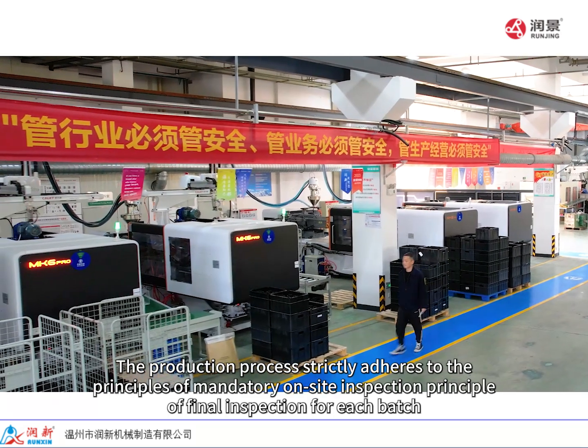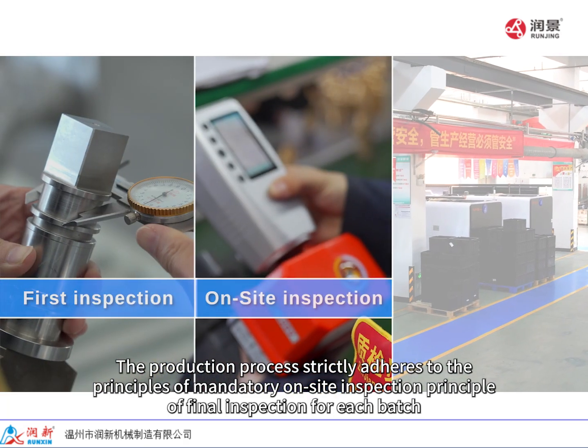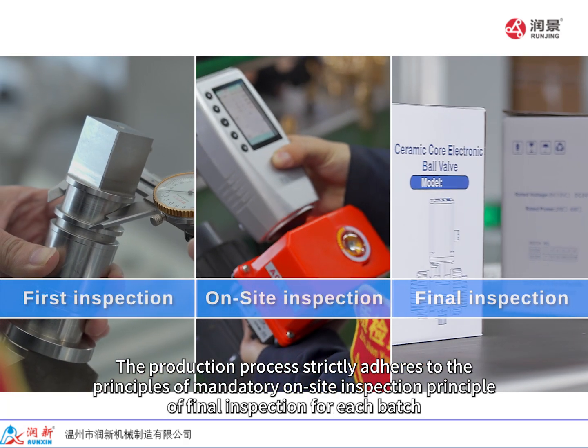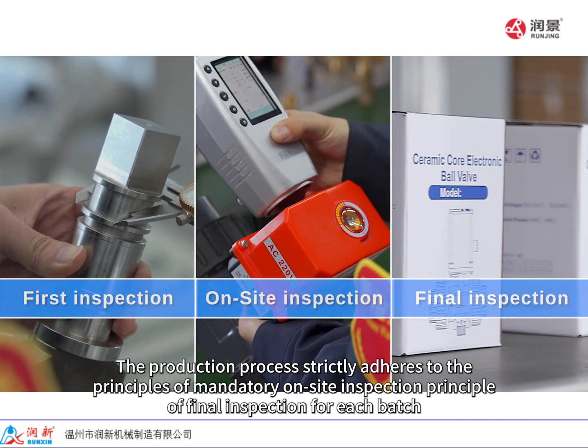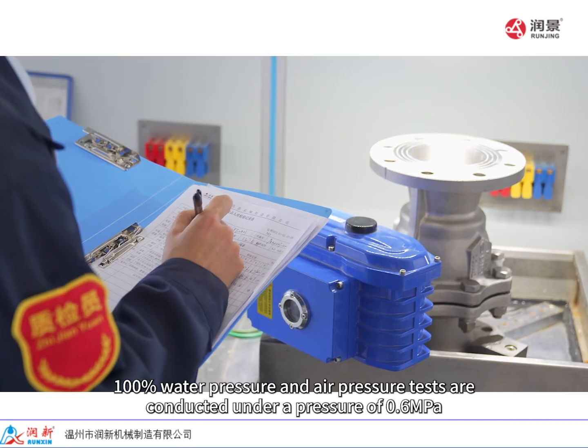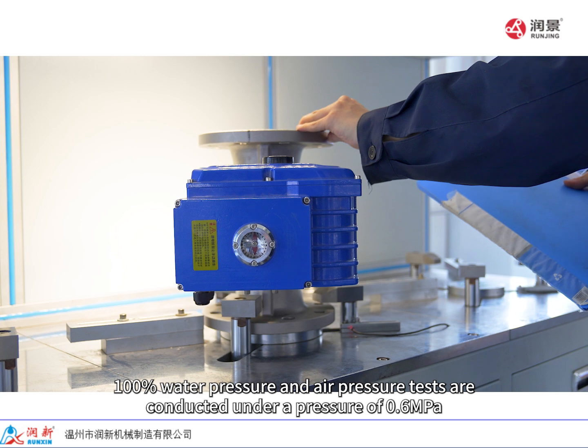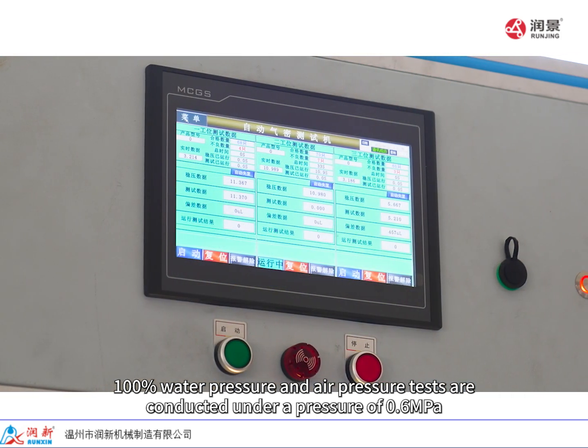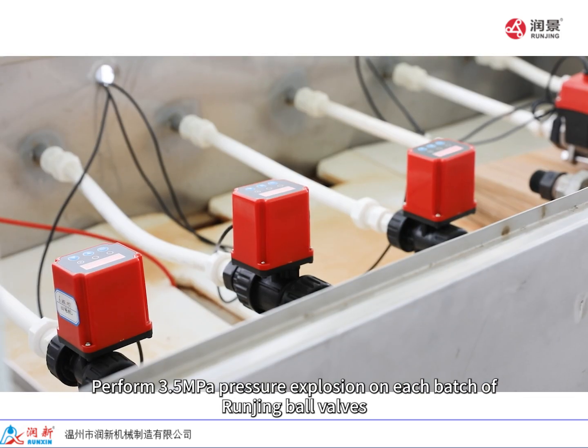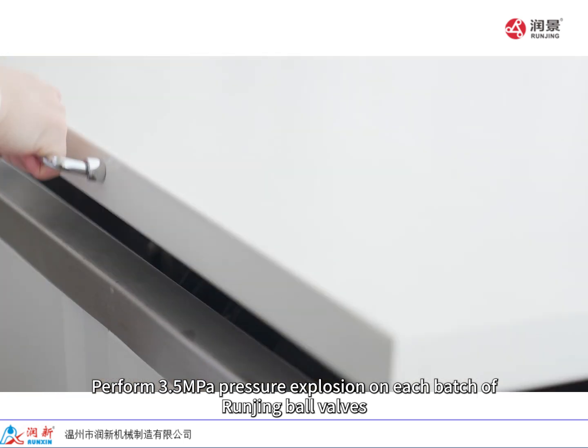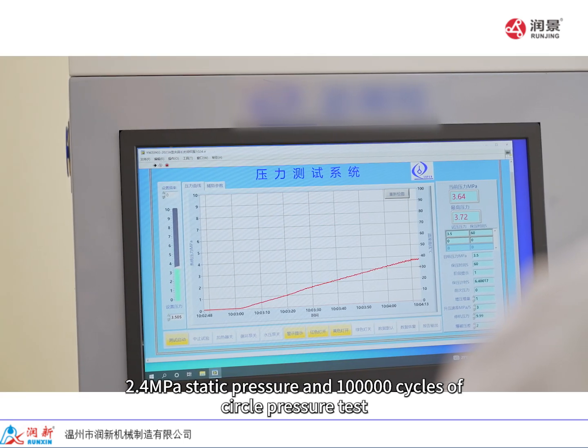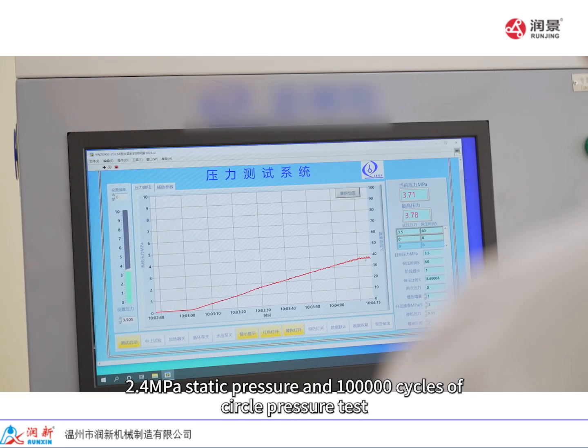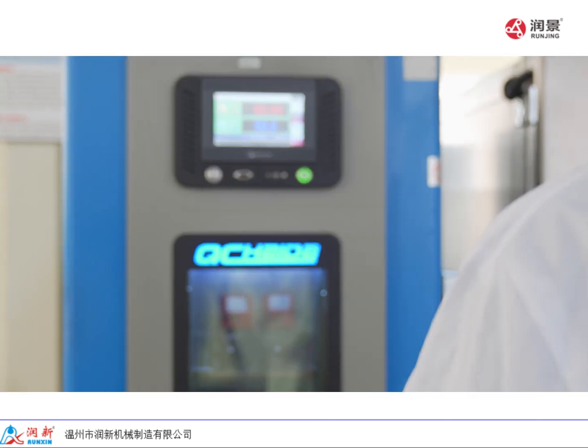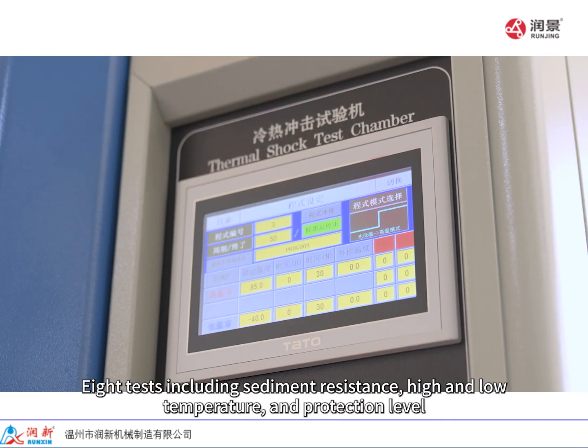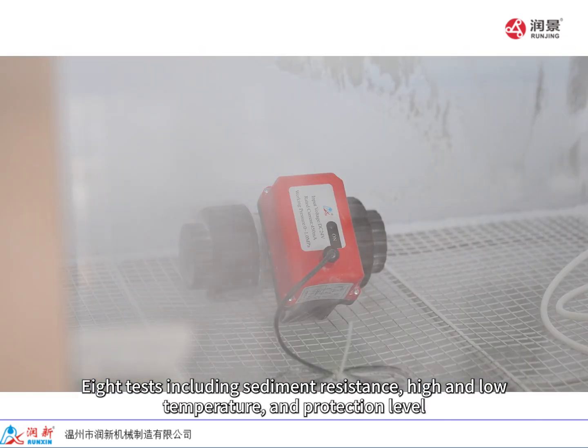The production process strictly adheres to the principles of mandatory on-site inspection and final inspection for each batch. During the assembly process, 100% water pressure and air pressure tests are conducted under a pressure of 6 bar. Each batch of Runjing ball valves undergoes a 35 bar burst pressure test, a 24 bar static pressure test, and a 100,000 cycle pressure test, along with 8 tests including sediment resistance, high and low temperature, and protection level.